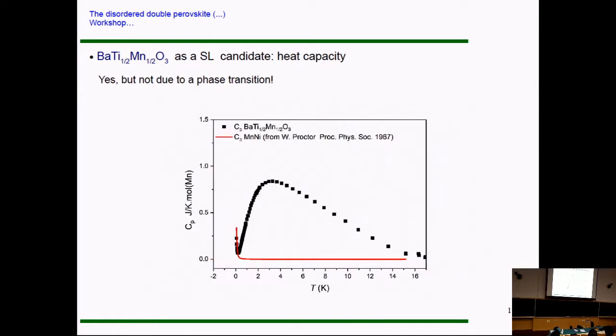Concerning this upturn that I was talking about, if you compare our specific heat at zero field, which we can measure down to 50 millikelvin, with the nuclear heat capacity measured for another compound, of course from a spectroscopic point of view this guy is very different from this guy, but insofar as specific heat is concerned, it's not so different, because electric field gradients and so on will not give a difference on thermodynamics, although in NMR you can see one. So here, as you can see, it fits very well, unexpectedly well. And it's apparent that this upturn is actually due to the nuclear heat capacity. And I will show later another idea why we don't have an ordered state; the muon results tell us that you don't have an ordered state.